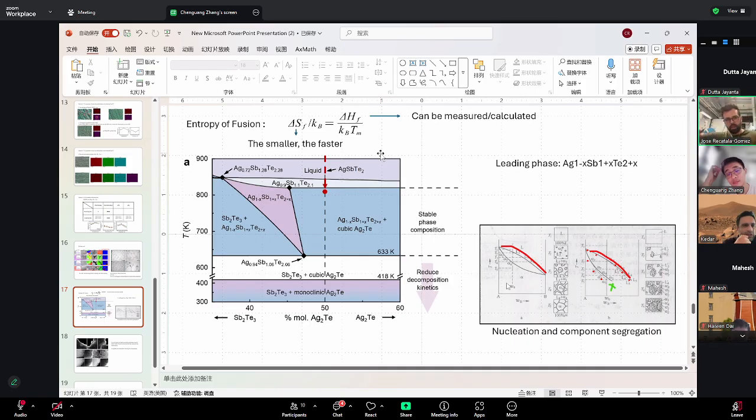And then how are you changing the X? Isn't the point here that you're starting at one point in this composition space? You're only at one point in the composition space, and then the different weight fractions that form are a result of the reaction. You can't control it. Can't we quench the sample at different temperatures here? Like you make 4 or 5 samples and just directly quench from T2 to room temperature, T3 to room temperature.